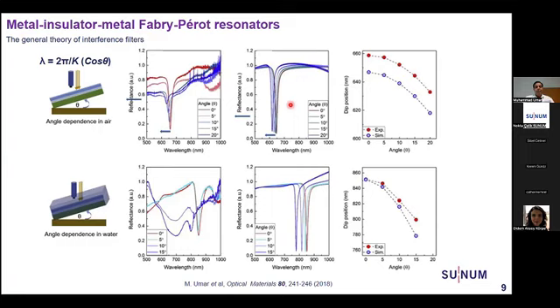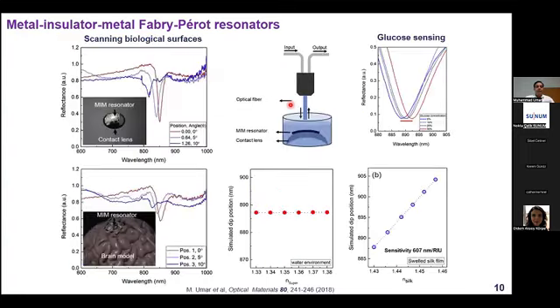We can use this angle-dependent characteristic of the devices to scan biological surfaces. For example, we put it on a contact lens and move the light source, and at different positions we see the resonance dip changing to the blue side because of the curvature of the contact lens, as well as when we conformed it onto the human brain model. Basically, in the previous slide, we used a photoresist as a sacrificial layer. We dip the sample in acetone to remove it, and then conform it onto the contact lens and brain model. So these devices can be conformed, and their thickness is just around 400 nanometers.